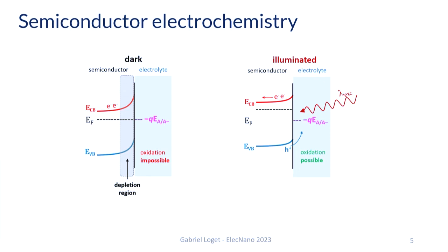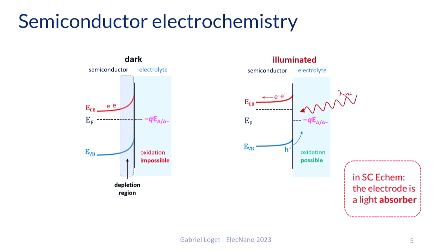However, under illumination, if you irradiate this semiconductor, and this is very important, with an optical energy higher than the band gap of the semiconductor, we are going to generate electron-hole pairs. The photogenerated minority carriers, in this case holes, are able to transfer through the interface and oxidize our redox species. So under illumination, we have an electrochemical activity which is triggered by illumination. What I would like you to remember is that in semiconductor photoelectrochemistry, the electrode is a light absorber.